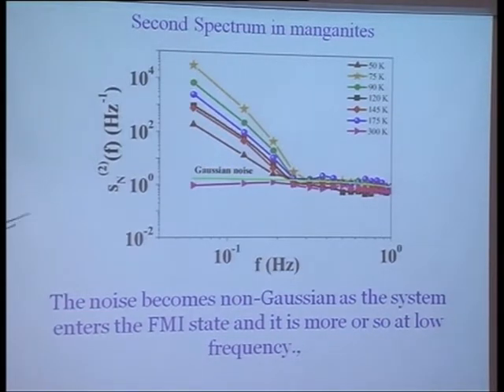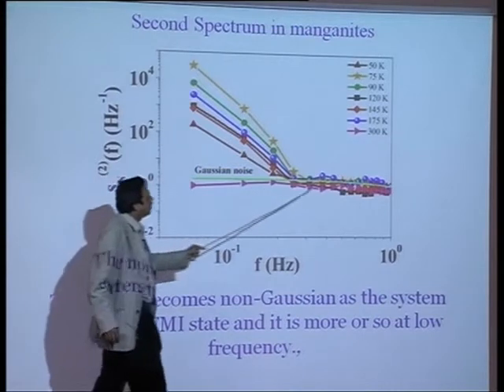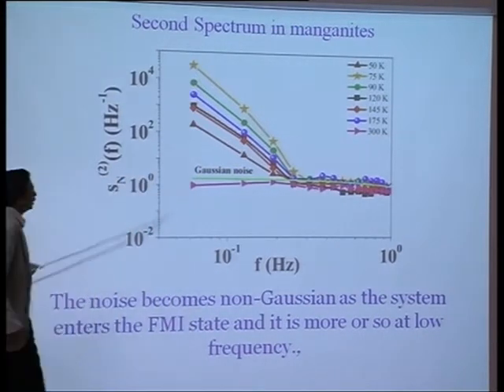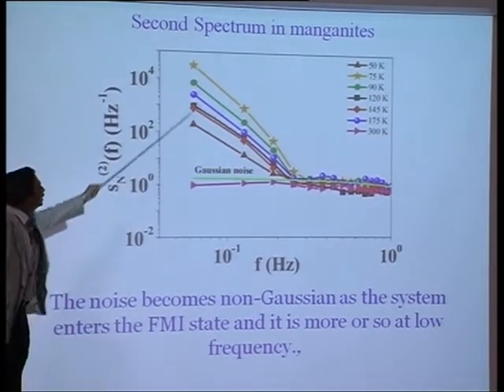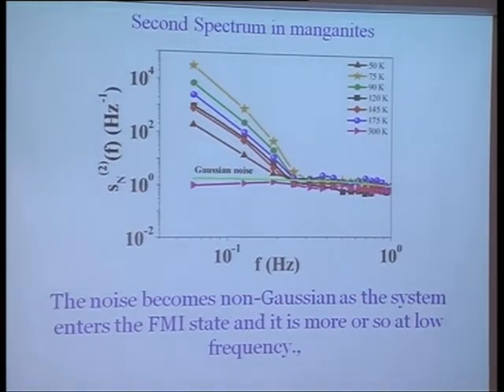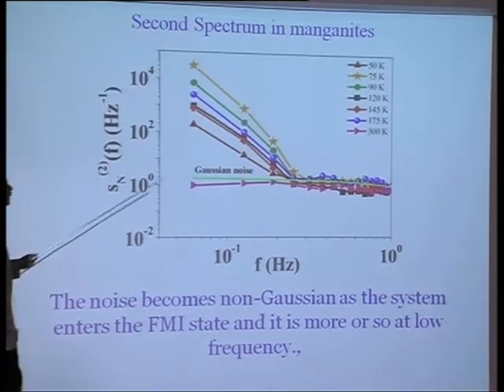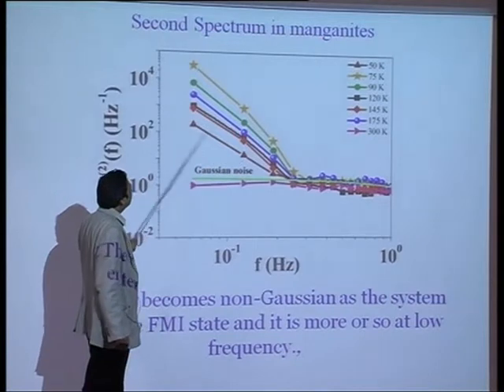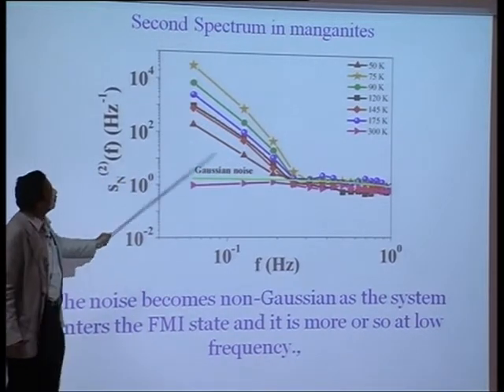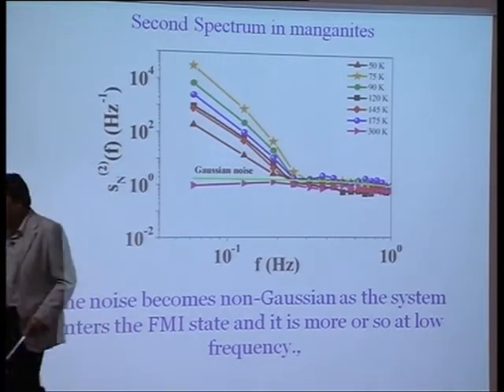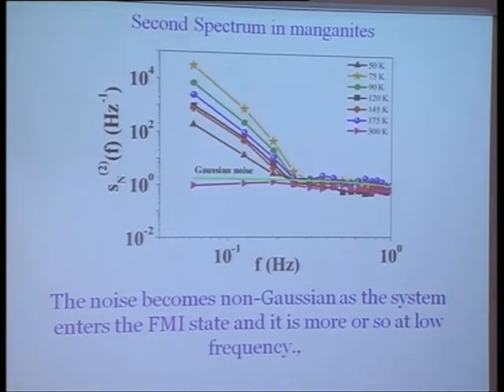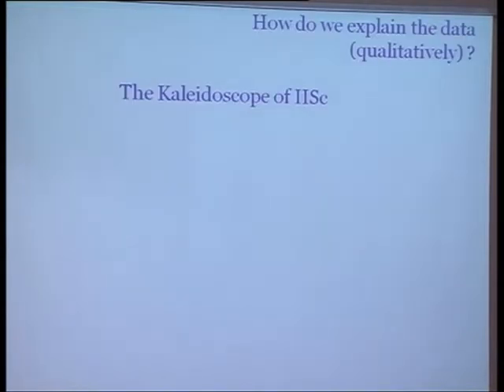If the noise is Gaussian and you calculate the second spectrum, I should be expecting this thing over here. But we do find that as we start cooling down, there's an enormous contribution coming from the non-Gaussianity factor. You find that even near the higher temperature, you have some contribution coming from the non-Gaussianity. Some of it can be a little artifact, because you have a finite bandwidth in which you are working. So how do I try to explain the data?